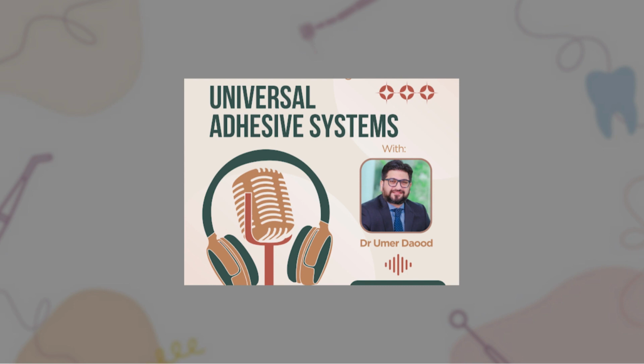Can you comment on the bond strength of universal bonding systems? What is the evidence? Yes, of course. So talking about evidence, to begin with, Wellington et al. in 2015 published a systematic review in the Journal of Dentistry. They stated with evidence that the enamel bond strength of universal adhesives is improved with prior phosphoric acid etching, right? So they're using the universal adhesive system with acid etching done before.